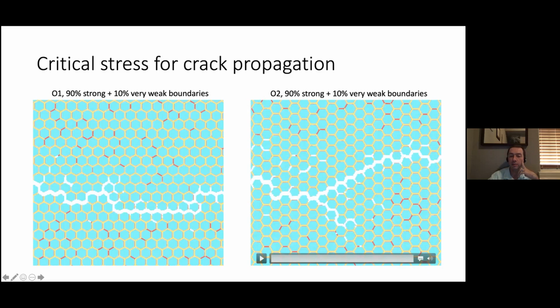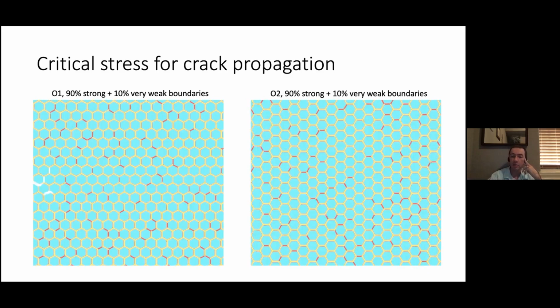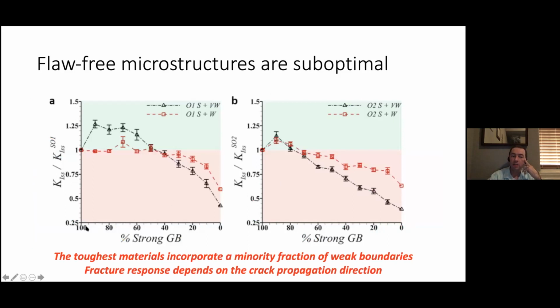The upshot is that now that we've figured out how to do these simulations and how to analyze them and figure out the critical stress intensities, we can actually plot those critical stress intensities as a function of the fraction of strong grain boundaries versus weak grain boundaries. And we get to a very interesting conclusion. So this is the critical stress intensity normalized by the stress intensity for a uniform microstructure that contains only the strong boundaries, okay?